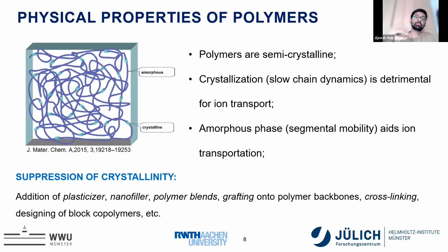And if you look at the complete polymer electrolyte scenario, you will see that most of the modifications in the polymer systems have been contributed by modifying the crystallinity of the polymer system. For example, here you can see that by adding plasticizers, nanofillers, or blending the polymer, grafting the polymer, or cross-linking, or making different kinds of blocks of polymers, you can achieve different morphology and you can control the crystallinity of the polymer system. Thus, you can improve the ionic conductivity.